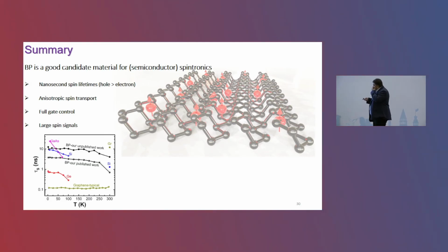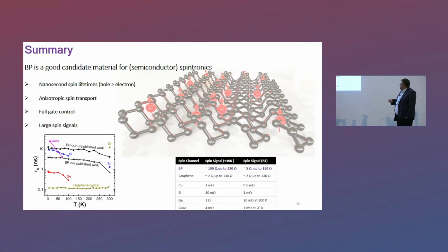And let me show you here first the spin lifetimes compared to the other star materials. So here I already listed materials like silicon, gallium arsenide, germanium, graphene, etc. Indeed, only our group has been working on black phosphorus, so it's a relatively new material for spin transport. But what we do see is that spin transport properties are already comparable, even better than the state-of-the-art materials. And another important feature of black phosphorus, I do believe, is the observation of extremely large spin signals. We perform this with a four-terminal geometry, and compared to, for example, even graphene, we do observe significantly larger signals. And this is also quite helpful in terms of using this spin transport for spin torque studies, etc.